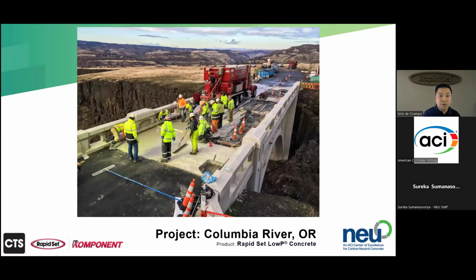We have another option for corrosion inhibition: Low P, an admixture CTS has available, called our Low P admixture. It's available as both a powder and a liquid. This is an example of a Low P concrete bridge deck in Oregon over the Columbia River, another alternative to latex using the same concept. Low P is added and inhibits penetration of water carrying chlorides into the concrete, keeping chlorides from brackish water or de-icing salts from diffusing in and attacking the steel reinforcement. Again, this is just another way to extend service life and keep the material in service as long as possible.